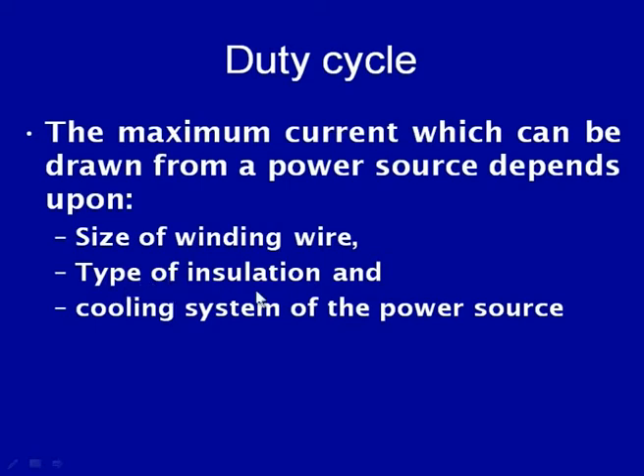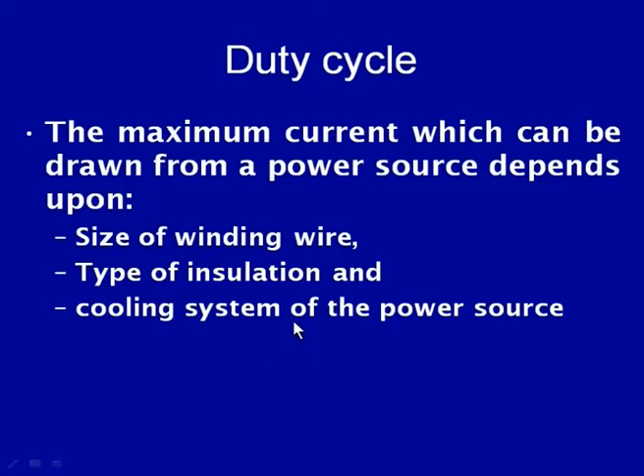Similarly, if the insulation of the coils and cable is good, then it will be able to sustain the electrical resistance heating for long. It will be able to draw the higher current without getting damaged. Similarly, if the cooling system is effective, it will be able to extract the heat being generated because of the electrical resistance heating when welding is done continuously at the high current.